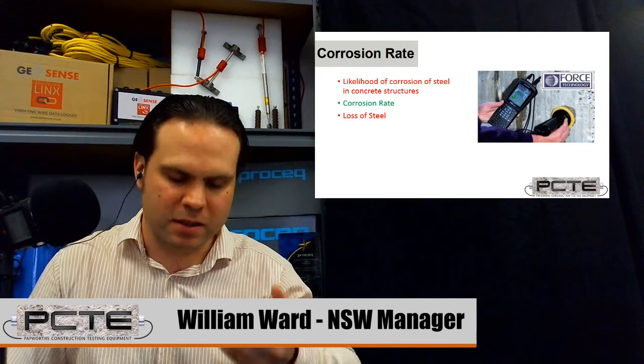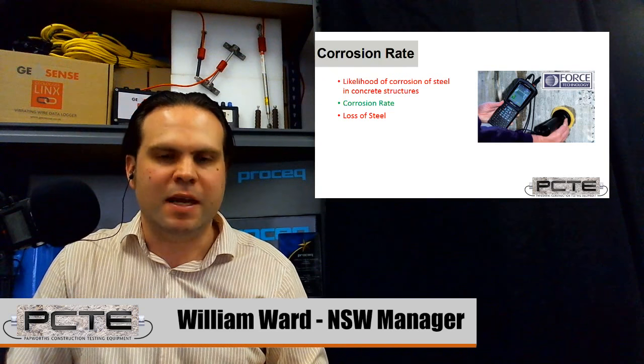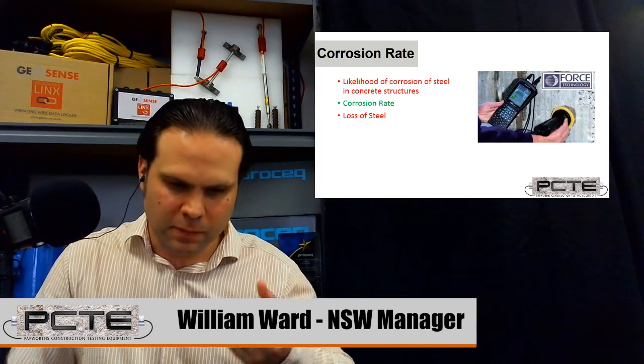Now, corrosion rate measurements, polarization techniques in particular, are our second tool we can use to evaluate corrosion in structures, and they're the one that gives us that corrosion rate. And that's a different measurement. This is a system that takes what's known as a galvanostatic polarization measurement. A current is applied and it measures the change versus the same half-cell potential measurement while a current's being applied. In particular, the standard mentions polarization techniques. So do take that into account when considering your choice of corrosion rate measurement equipment.